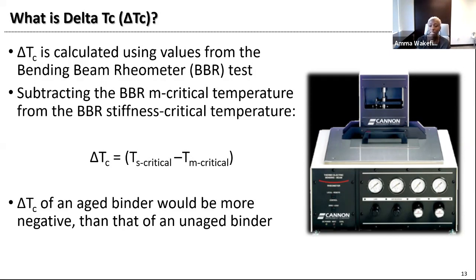What can you learn from delta TC? Delta TC can tell you about the binder, depending on what the value is. So the delta TC of an aged binder would be more negative than the delta TC of an unaged binder. With the delta TC of an unaged binder, you would be more comfortable to say that it wouldn't be as susceptible to the distresses that I mentioned. Whereas a very negative delta TC would tell you that this binder would be more susceptible to block cracking, raveling, and age embrittlement distresses associated with that binder. So it gives you a good idea if you're comparing the values.